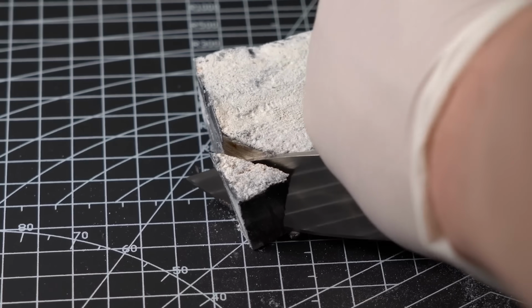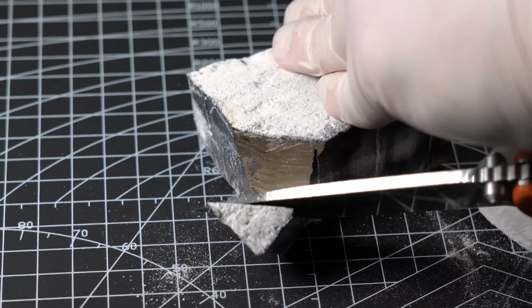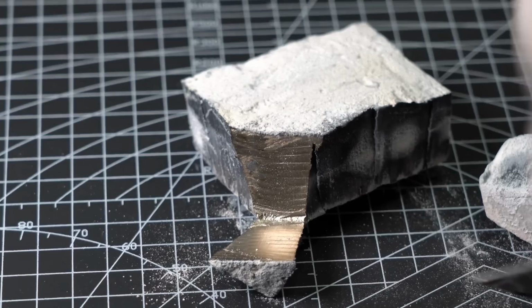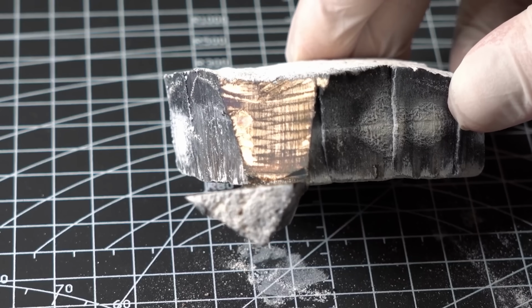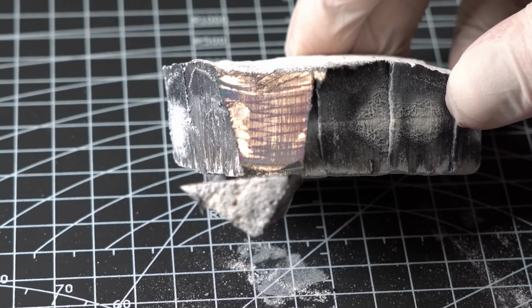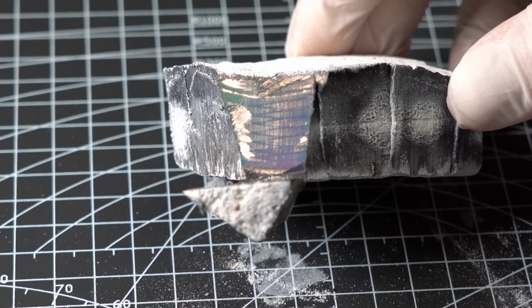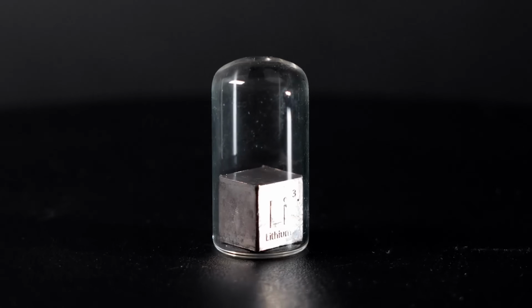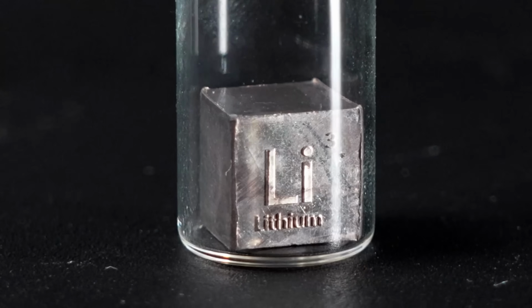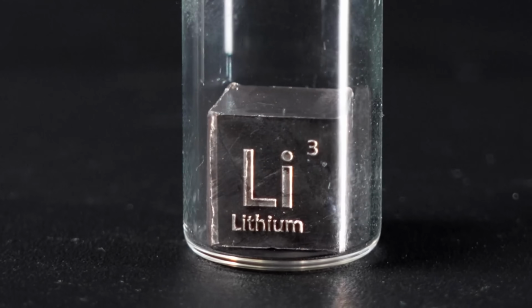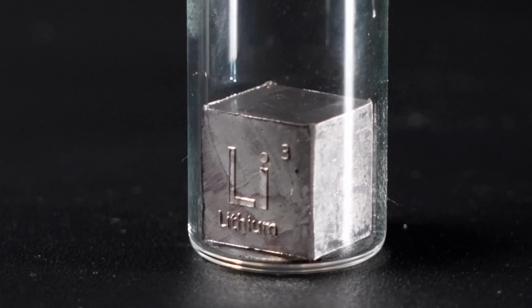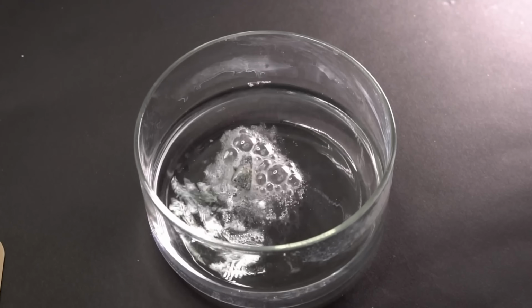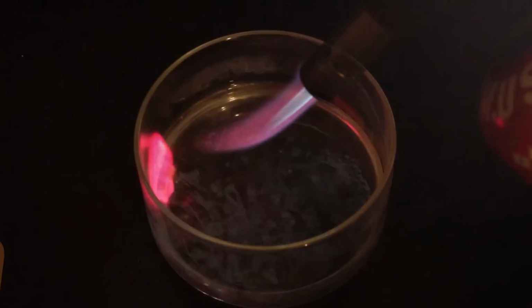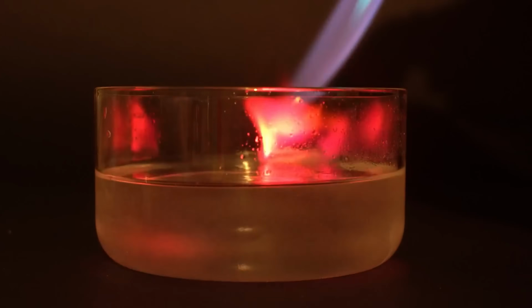The freshly cut lithium quickly oxidizes in the air, covering with a black layer of lithium nitride formed by the reaction with nitrogen, as well as with a white deposit of lithium oxides and hydroxides. The unoxidized surface of metallic lithium can be seen only when the metal is stored in an ampule with an argon atmosphere. In addition, lithium reacts with water, releasing flammable hydrogen. When ignited, it burns with a beautiful red color caused by lithium ions.